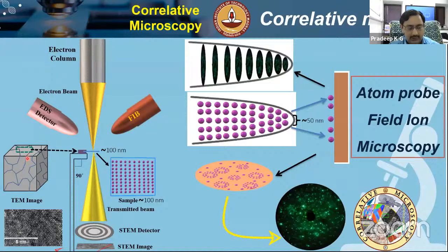So we can rotate the samples, we can tilt the samples in any direction as it requires, and look through their three-dimensional sectioned image. But we have to remember that each sectioning that we are doing is a destructive method. That means that particular region, what was originally present, would have been lost. So if we do a serial section imaging like this, even on a bulk scale, using the existing infrastructure, we'll already be able to get a three-dimensional sequential imaging, which will then be reconstructed to look like this. So this is more or less in the micrometer range scale.